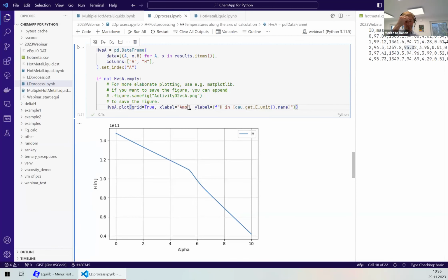What you see here already is we have one constant slope. That is the regime when we are actually burning the carbon, creating carbon monoxide. And then we have a change in slope as we oxidize the metals. And then we have, again, a different, but again constant slope. And that is the point when we're oxidizing iron, which is something we don't want to do, obviously.